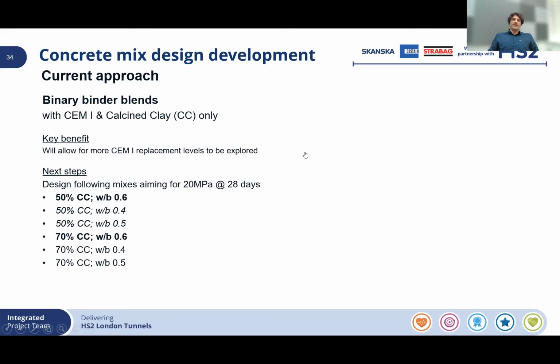So our approach to mix development first was, as we call them, binary blends. So we want to use just Portland cement and calcined London clay. And as we said, we're targeting low strength applications, 20 megapascals at 28 days. This represents a substantial volume of concrete that's going to be used in the project, like for walkways or for mass concrete applications. And we start from the least favorable mixes, for example, those with high water binder ratio, 0.6, and 50 and 70% replacement of Portland cement with calcined clay, and then start considering other water binder ratios and replacement levels as well. Next slide, please.